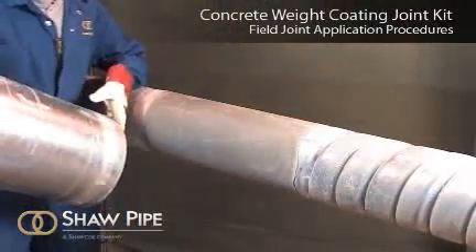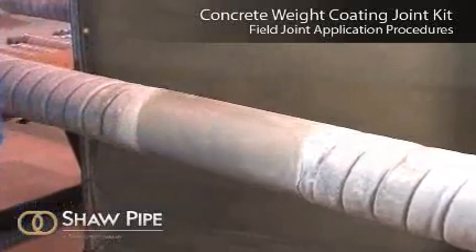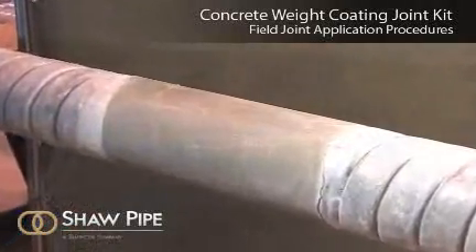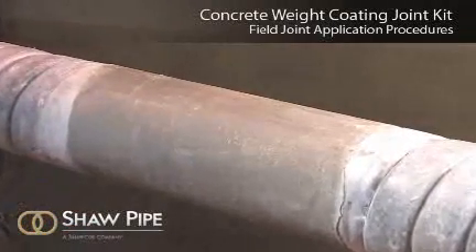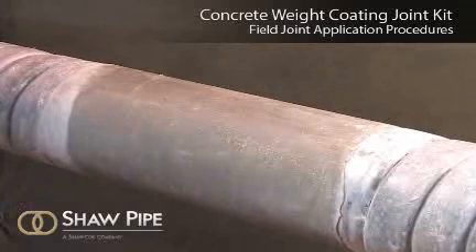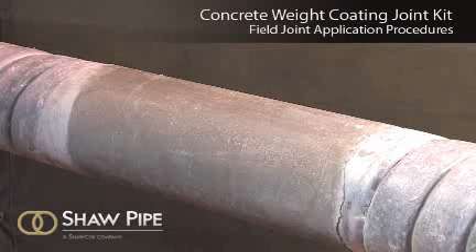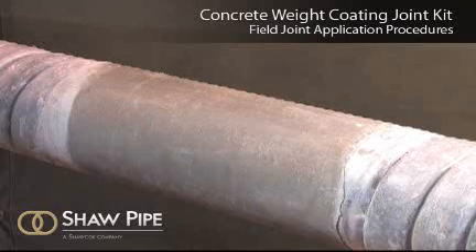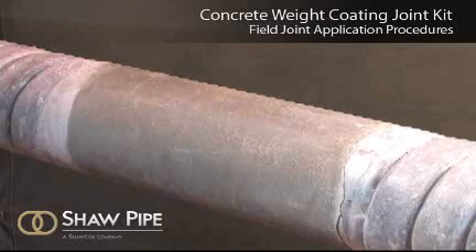Note: the grout must be protected from freezing for a period of at least 24 hours after the initial mixing. In colder weather, below 13 degrees Celsius, the grout must be protected for longer. 2 to 3 days is recommended. Now the joint is ready for lowering in and backfill.